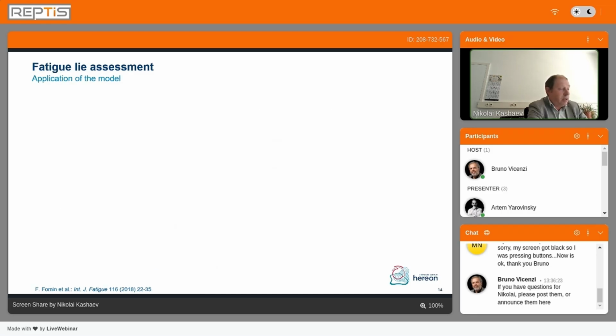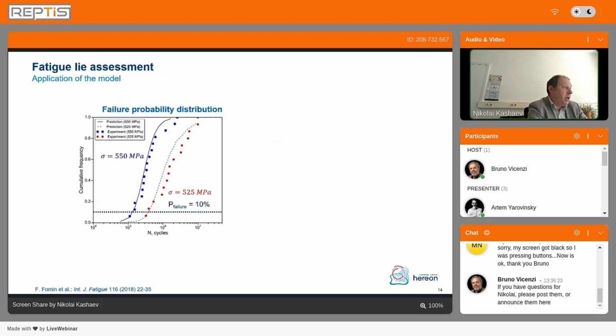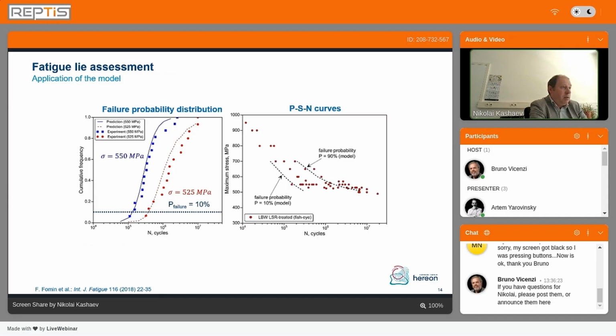We validated this approach, and for example, using 16 specimens tested at different levels of cyclic loading, 525 and 550 megapascal. And here you see the points, the experimentally obtained results, continuous curves, blue one, and dashed curves, red one, are the results based on our model. You see we are in a very good agreement,